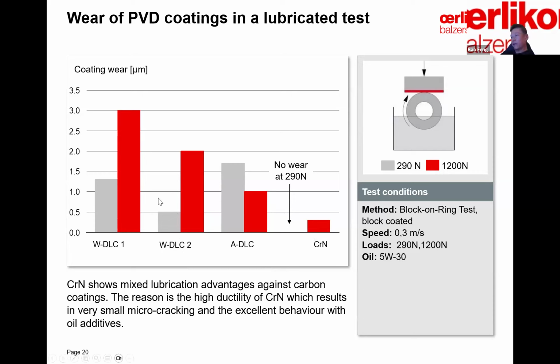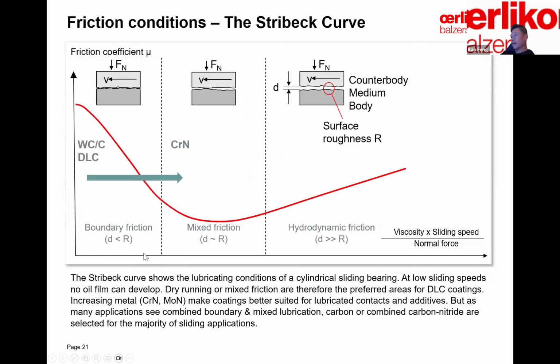And surprisingly, because we mentioned the low friction and wear resistance of DLCs, but surprisingly, the chrome nitride coating in this case, at low contact pressure level, has almost no wear. So we did a further study and found there are micro cracks on this particular chrome nitride, which facilitate a lubrication reservoir at the contact. We put that on a classic Stribeck curve.